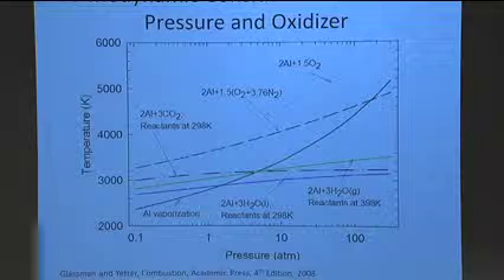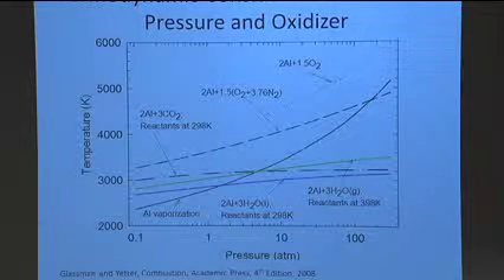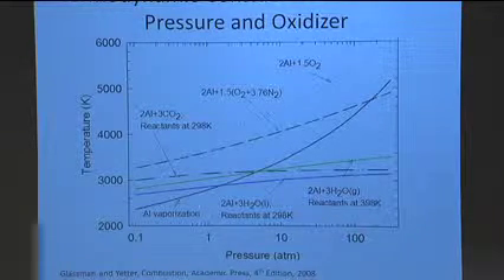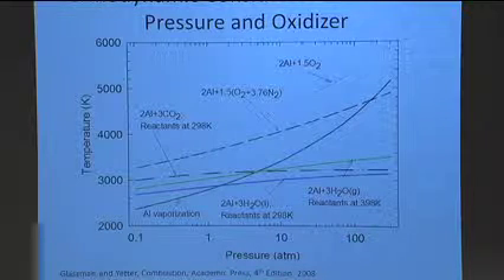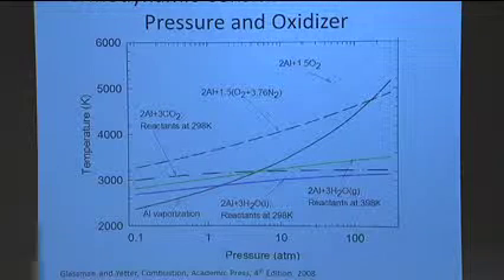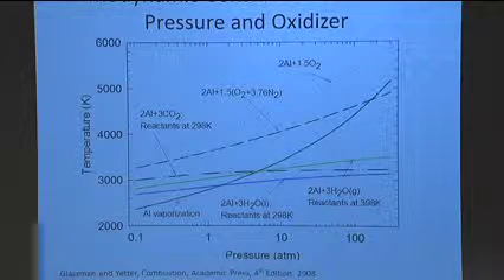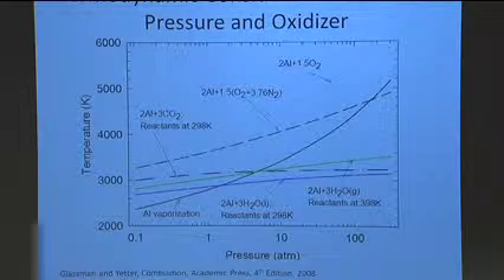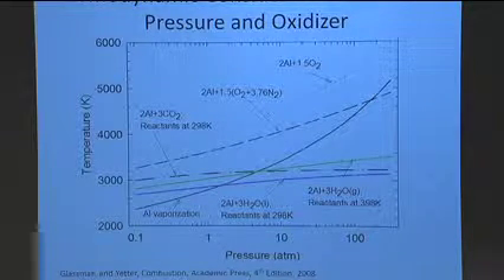Now I ask the question, well, suppose I was doing this in a different oxidizer like CO2 or water vapor. What I'm ending up doing here is I'm changing the energetics of that reaction, the heat of reaction. I'm actually lowering it. And what you see as a consequence of this, if I try to burn aluminum in liquid water, what I'll find is that at very low pressures, I'm back to the original situation where the flame temperature is higher than the vaporization temperature, so I could have a gas phase process. But just slightly above 1 atmosphere, I get this crossover effect to happen. So now if I just raise the pressure a little bit, I'm going to be getting to a situation where aluminum wants to burn heterogeneously with, say, liquid water, or even water in the vapor state.